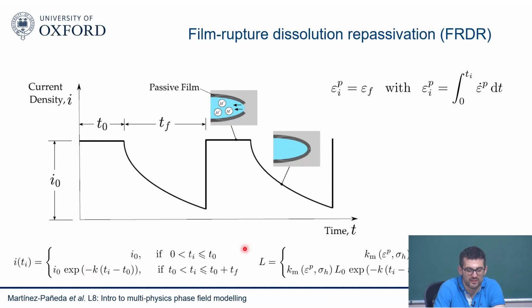So again, the way we implement this into the model is that we define an enriched mobility coefficient that captures what we expect to see with the current, because mobility coefficient and current are proportional. And then you may have this mechanical enhancement term that we saw before. And then you have either the corrosion of the bare metal or this degradation of the corrosion based on this parameter k. So we have to add an extra parameter. And again, this is not something that I'm completely happy about. I wish I had something more physically based than this k thing. This k thing sounds a little bit like the alpha beta that I was saying at the beginning. So you do an experiment to fit that k film.